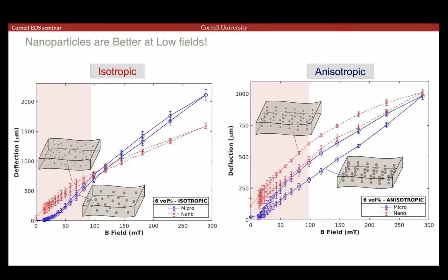In the isotropic films, if they're randomly distributed, then you can't really guarantee that the coupling between them is going to reinforce the magnetization. They will probably cancel. We have a lot more details in our paper about why the isotropic one tends to deform more overall in this case, but I'll not talk about that now. But in the isotropic case, you have an overall averaging of the particles that reduces your net moment, but then at the same time, these ones will only be responsive to a field gradient.